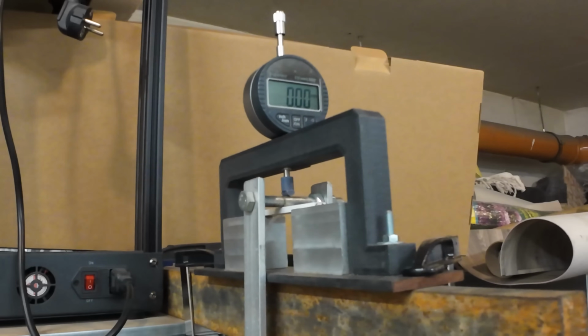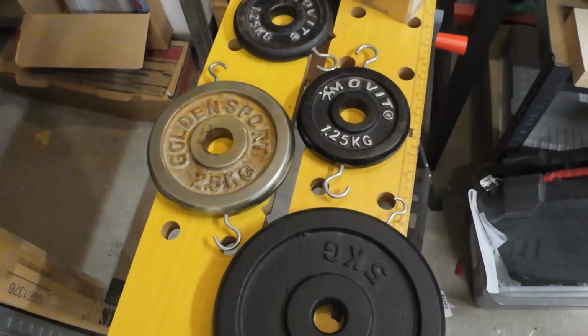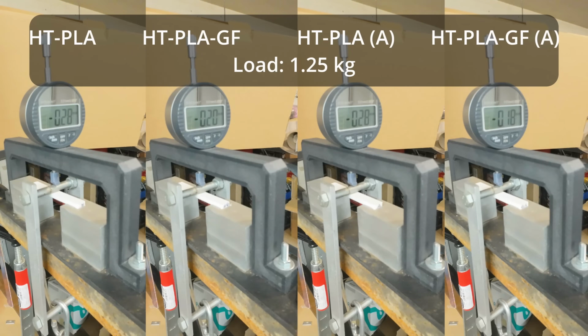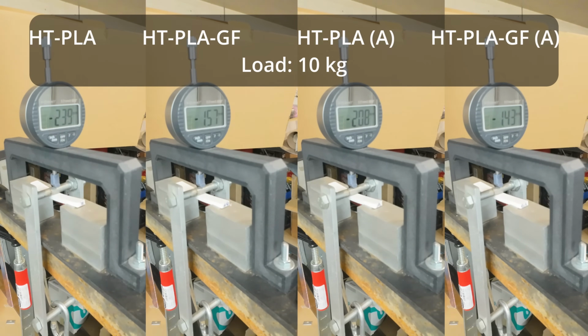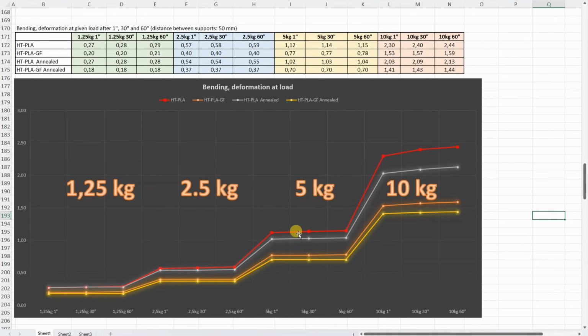Distance between supports is 50 mm, and these loads will be placed one by one, and I will measure the deformation after 1, 30 and 60 seconds. This is a deformation under 2.5 kilograms, under 5, later I will analyze the graph, and deformation under 10 kilograms. Smaller values are better. This is not bad, but we can see that the glass fiber versions are better compared to the non-reinforced versions, and also we can see that annealing helped in both cases.